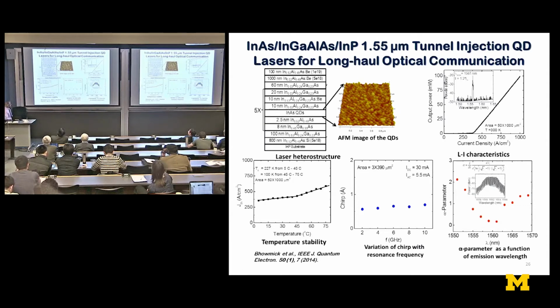These are 1.55 micron lasers. Now, when you try to grow quantum dots on indium phosphide-based heterostructures as opposed to gallium arsenide, you can't grow quantum dots. From the kinetics in the different directions, they tend to grow as what we call quantum dashes, little segments of islands. And it took my students a while to actually figure out the conditions of how to grow real quantum dots. But once we got them, these results were repeated in Germany, and they're still being worked on.